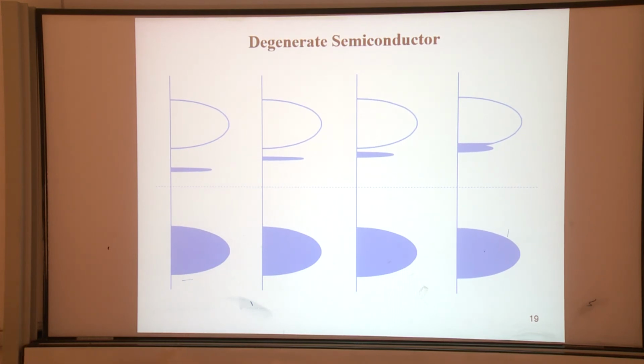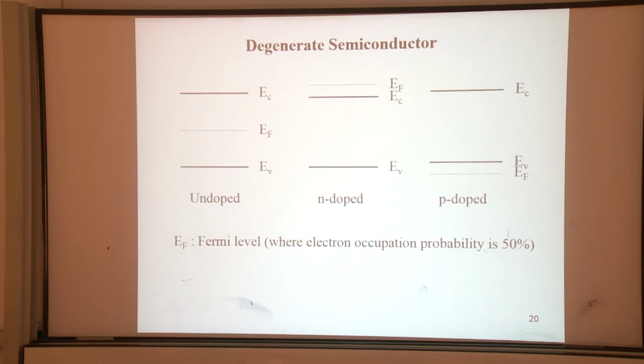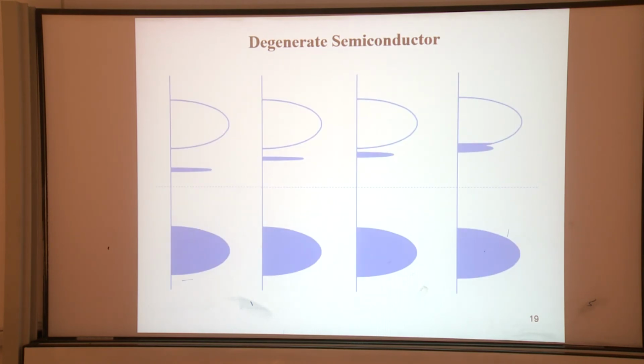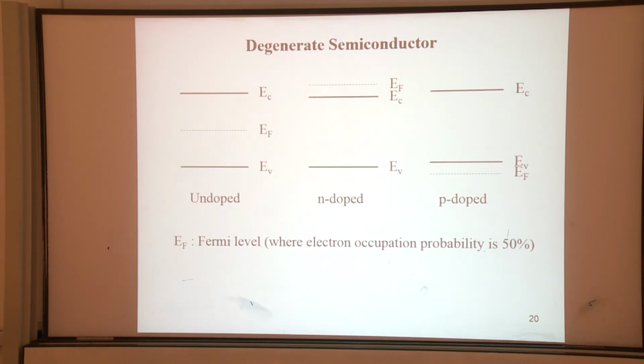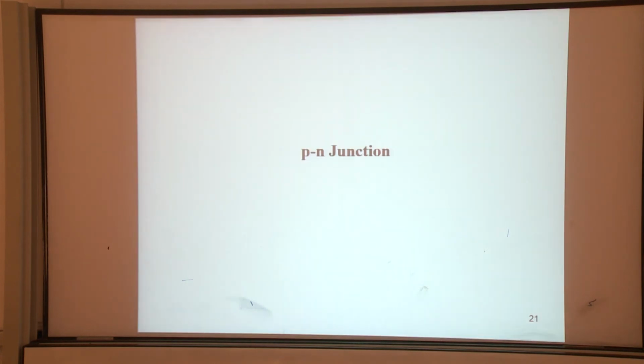Transparent conducting material can be used in TVs, LED lighting, or imaging. We need the light to pass through the medium while it is conducting. So usually we use this mechanism instead of using metal. Metal, although it's conductive, is not transparent at all. Okay. So we call this a degenerate semiconductor. In a degenerate semiconductor, the Fermi level is higher than the conduction band, because the conduction band drops due to the overlapping of the defect level with the conduction band. And for a degenerate p-type semiconductor, the Fermi level goes below the valence level.